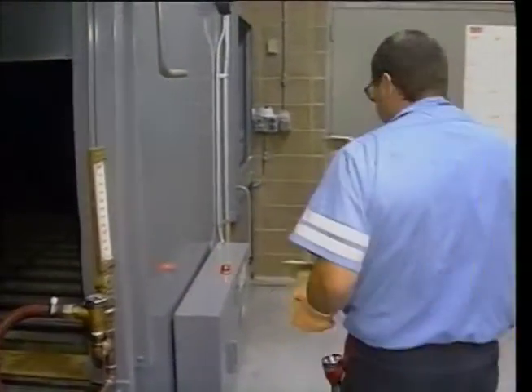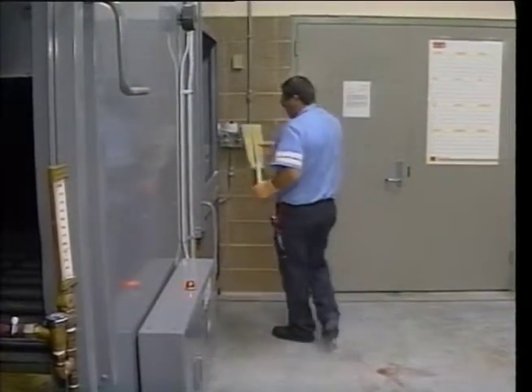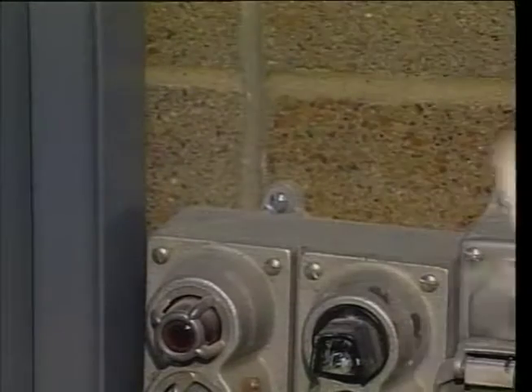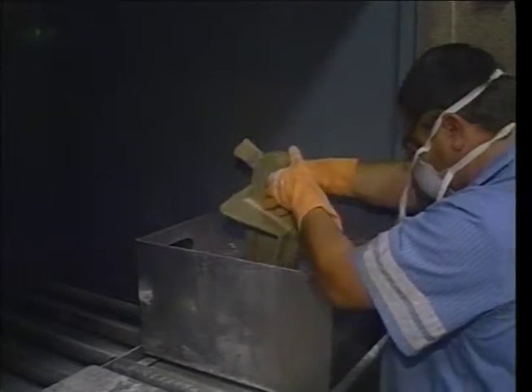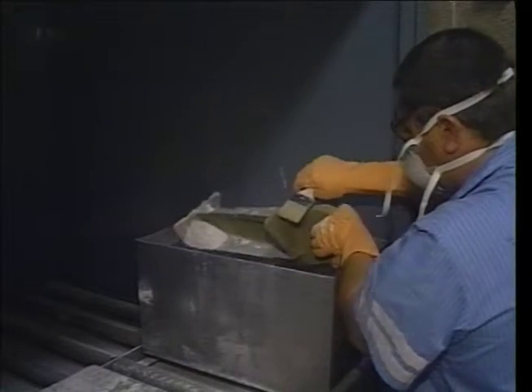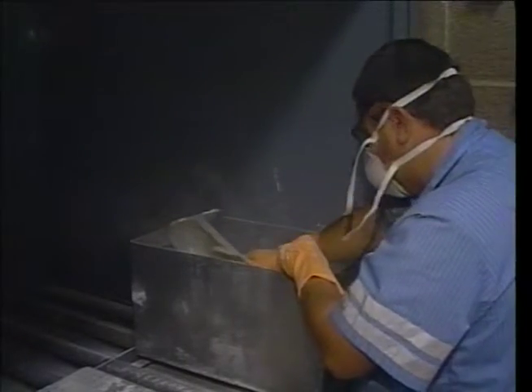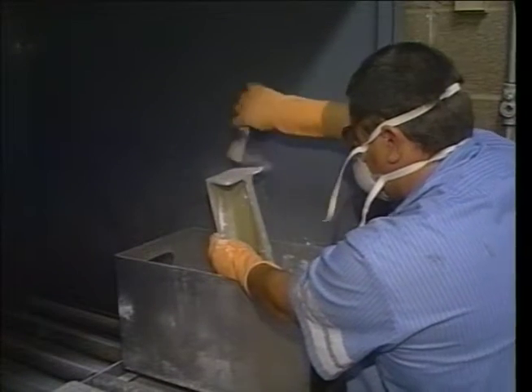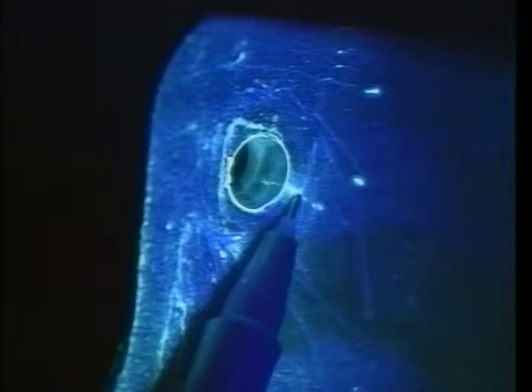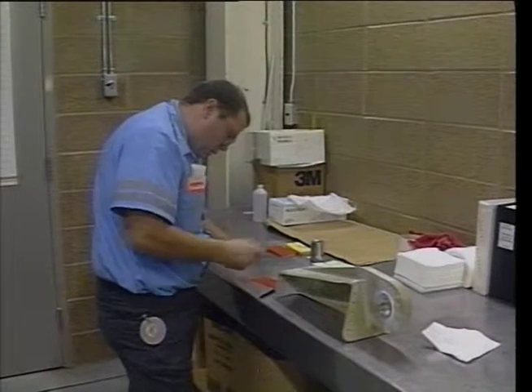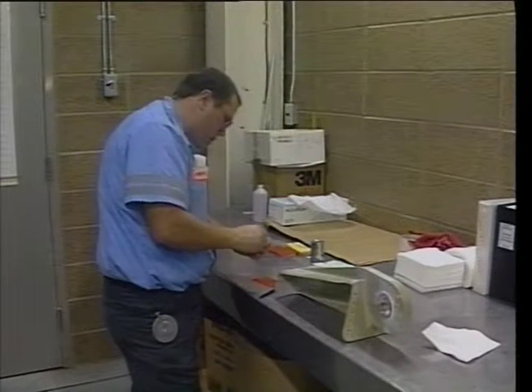After the part is heat dried, it's subjected to the developer, in this case, a fluorescent powder type developer. As shown, gloves and air mask safety precautions are recommended. Under ultraviolet light inspection, the developed dye shows up as a brilliant yellow-green color. The dye penetrant technique will detect surface porosity and fatigue or stress cracking, but it cannot see inside the structure.